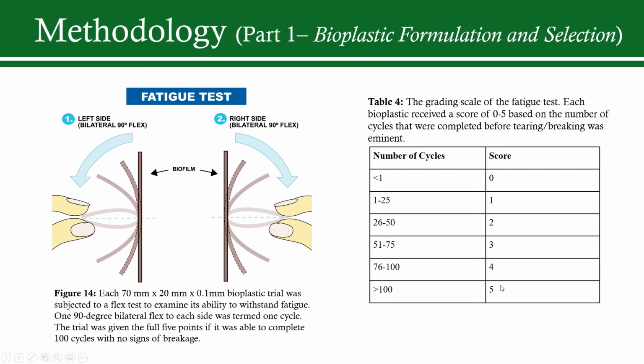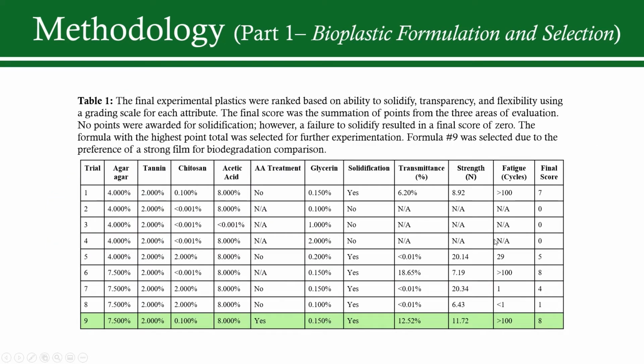And finally, a fatigue test involves subjecting each film sample to continuous 90-degree bilateral flexes until breaking occurred, as shown in the diagram. And to the right is the grading scale for this test. So at the conclusion of the preliminary test, the points were summed, and whichever film had the most points would be the final formula. Formula 9, here in green, was selected despite the tie with sample 6, as strength was valued more so than transparency.